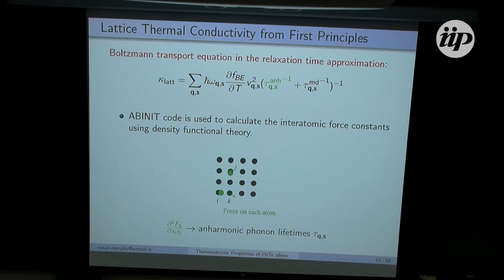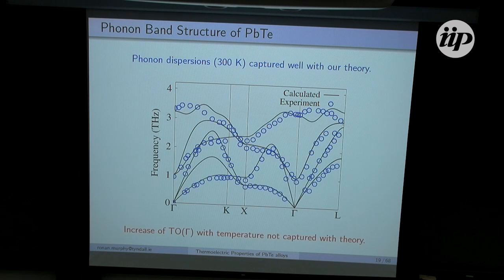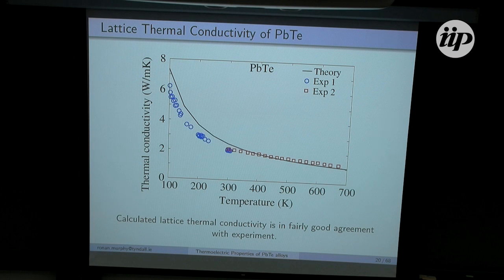So now the question is, how does this theory compare to the experiment? So I have here the phonon band structure again of lead telluride. Our curve is in black, and these blue dots are inelastic neutron scattering data captured at 300 Kelvin. And we can see we do get very good agreement between the experiment and our theory, with one very important caveat, and that is that since we're using DFT, our calculations are at 0 Kelvin, so we don't capture the temperature dependence of that TO mode phonon at the gamma point. And in reality, as you increase the temperature, that TO mode will also tend to increase upwards, which isn't captured. And that does play a slight role in the thermal conductivity.